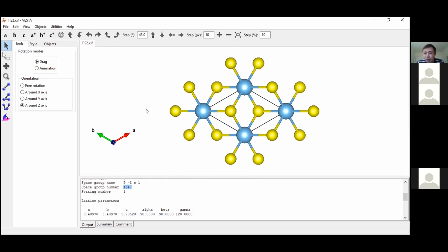And for lithium cobalt oxide, it's just the opposite. You start with the lithiated version, which is actually high temperature stable. It's synthesized at high temperature, it's thermodynamically stable. And you make the battery work by extracting lithium from lithium cobalt oxide. So actually they work by very opposite mechanisms.